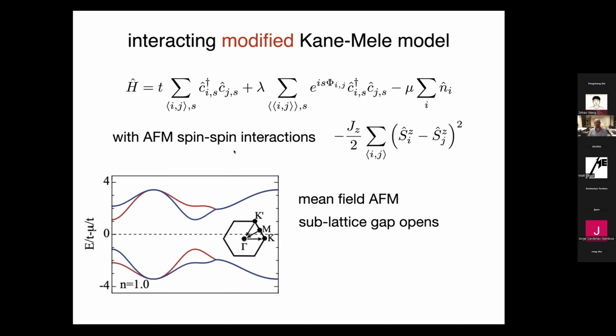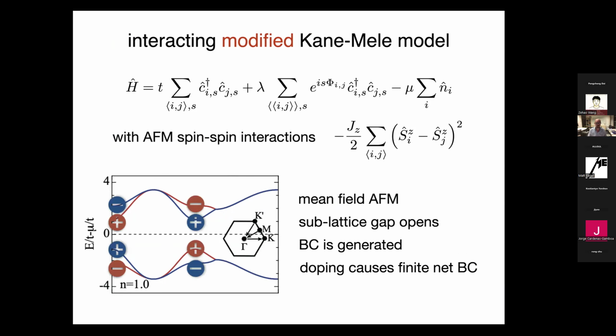And what we do is now introduce spin-spin interactions in this form, which is an interaction between nearest neighbor spins of Ising type. If I do a mean field calculation of this model, we see that there is a gap opening. This is a topologically trivial gap. It's due to the sublattice symmetry breaking. And if I look at the Berry curvature